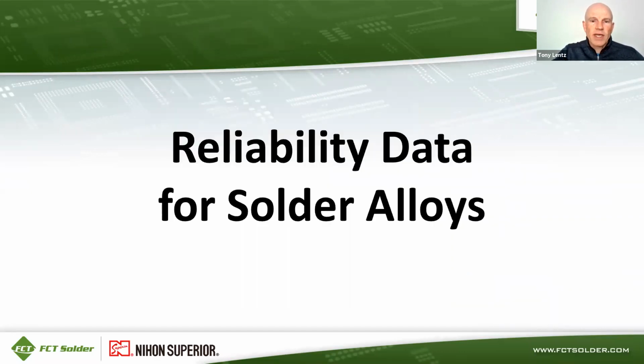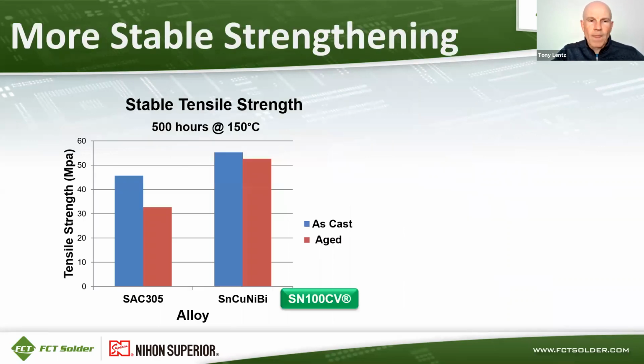So let's switch gears and get into some actual reliability data for these various solder alloys. So here's some tensile strength that was measured for SAC 305 versus tin, copper, nickel, bismuth, otherwise known as SN100CV. The aging that was done here is 500 hours at 150 C. The blue bars are as cast and the red bars are the aged numbers. So you can see the tensile strength drops for SAC 305 with aging, whereas with SN100CV, it remains very stable.